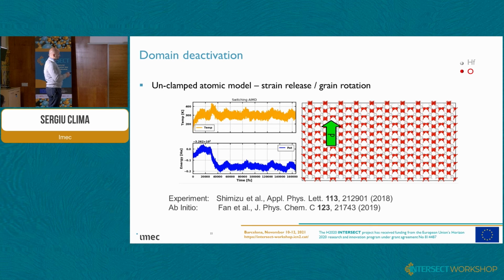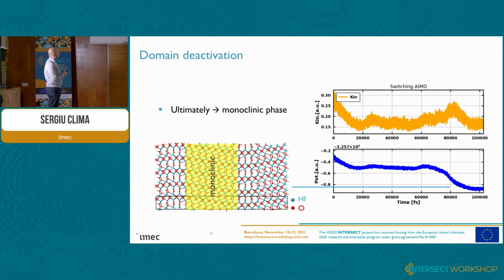So in principle, we can envision that this kind of 90 degree rotation of the domains could be happening while you switch many cycles, and then you lose the polarization because some of the domains switched orientation, or they switched to the monoclinic phase. This is basically showing what happened at the end of the simulation, where the ferroelectric orthorhombic phase switched to the monoclinic one.